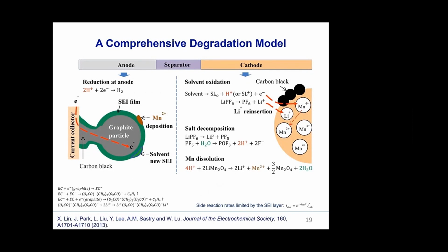As we mentioned before, various side reactions can occur in a battery cell, causing capacity degradation. We integrated SEI growth, lithium plating, manganese deposition on the anode, and solvent oxidation, salt decomposition, active material dissolution on the cathode side, and processes such as fractures. By considering the transport and balance of species and charges, we obtain a comprehensive degradation model.